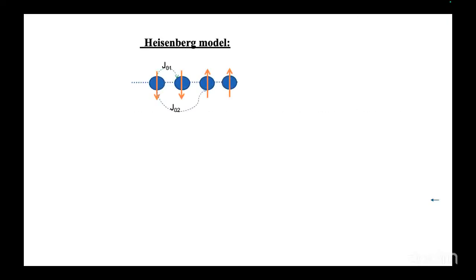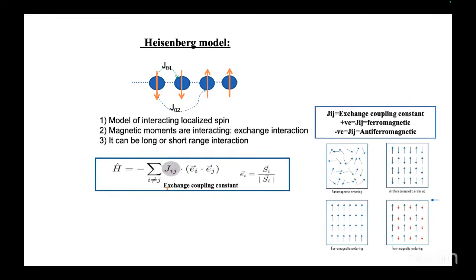After investigating the electronic structures, we did the magnetic exchange interactions. Before going into the results, I will briefly give an idea how I calculated the magnetic exchange interactions. We use the Heisenberg-Hamiltonian for evaluating the magnetic exchange interactions, which works on the principle that the atoms have localized spins, and these localized spins interact with each other, giving rise to exchange interactions. In a realistic system, one can have long range and short range interactions. So we can have nearest neighbor coupling or second nearest neighbor coupling and so on for the long range interactions. This is the Heisenberg-Hamiltonian, where Jij is the exchange coupling constant, summed over all the possible bonds, and there is also a scalar product of the two spins in this expression.